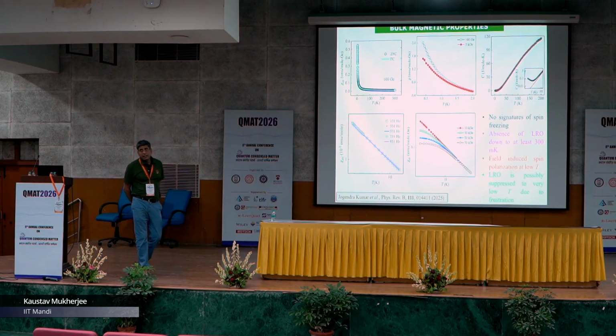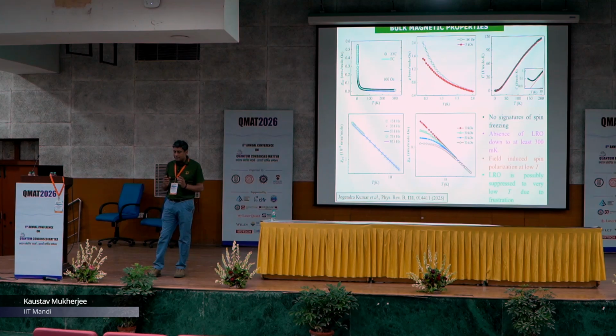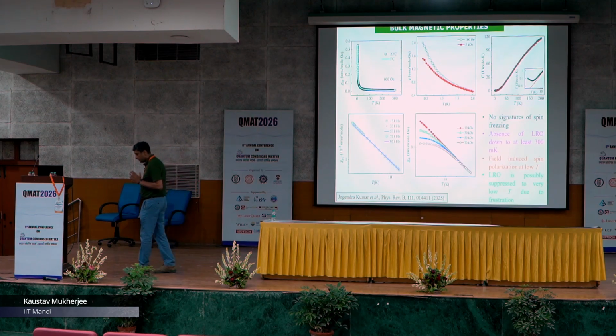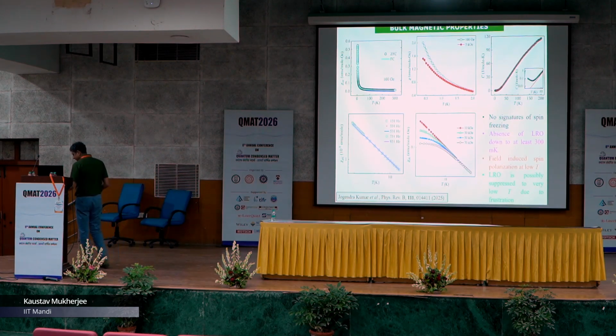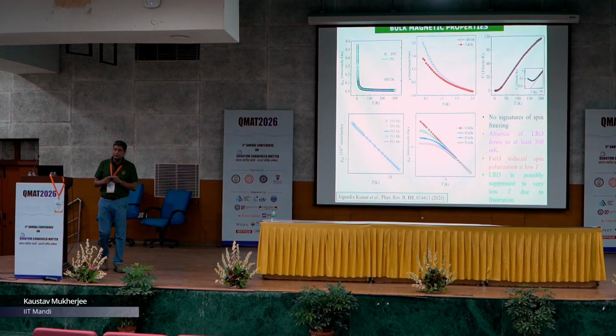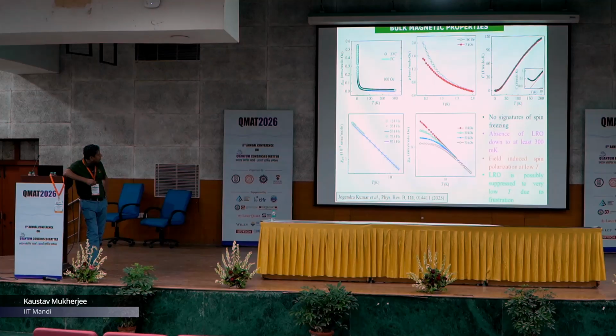As I mentioned, the fundamental signature is that there should be no long range ordering. So we did magnetization measurement as a function of temperature, chi DC, both in ZFC and FC mode, and what we see is that there is no magnetic anomaly and both the curves superimpose on each other. We also did AC susceptibility measurement at different frequencies as a function of temperature, and as you can see the AC chi graphs for all the frequencies are superimposing on each other. Now these two measurements were done up to 1.8 Kelvin.